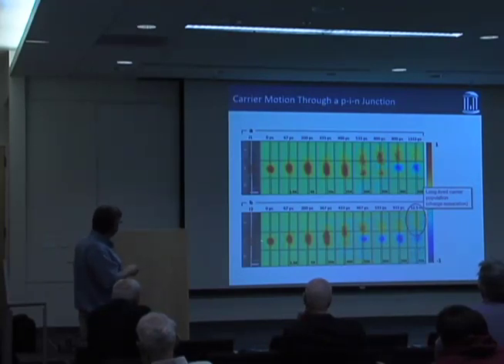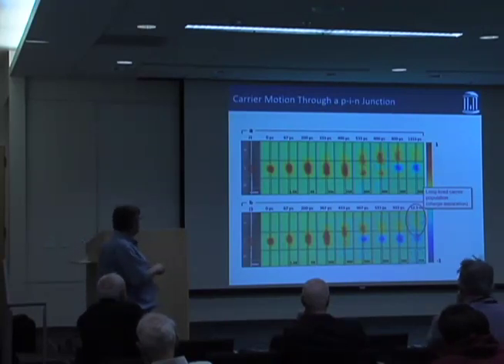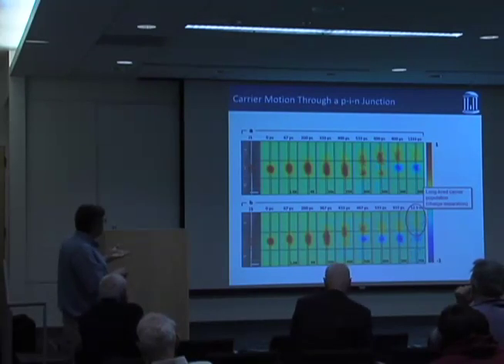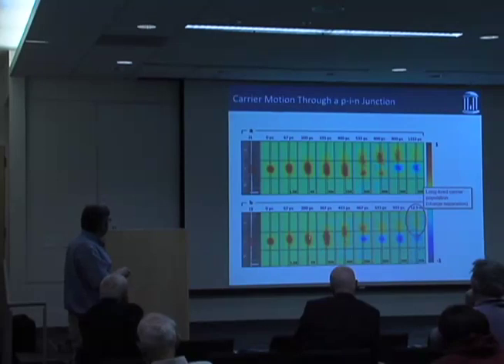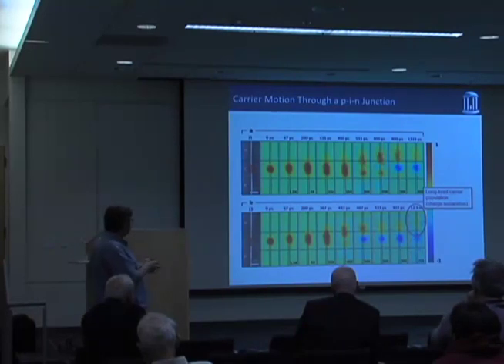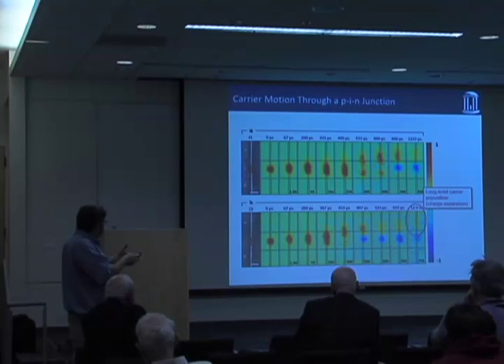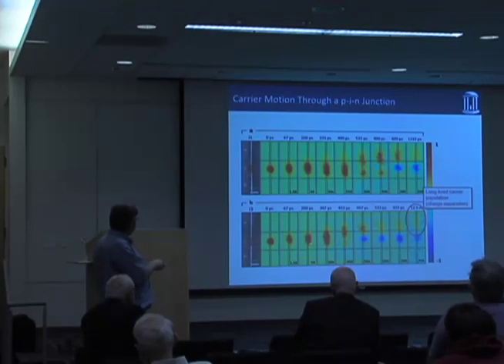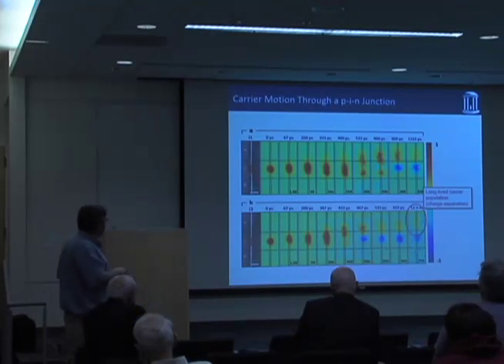So here are 2 examples that we got, or 2 different wires. And again, you see this signal that expands, reaches the boundaries of the undoped segment, and then becomes asymmetric with a long-lived signal in the N-type region. On one hand, we were happy because the signals were asymmetric, but what we had envisioned was that you create a bunch of electrons, and okay, this is our not knowing what we're talking about part, but what we thought would happen is they would just start marching across the intrinsic region in this field. But you don't see that. What you initially see is something that looks more like diffusion. And it's not until much later that you see the effect of the junction take over.